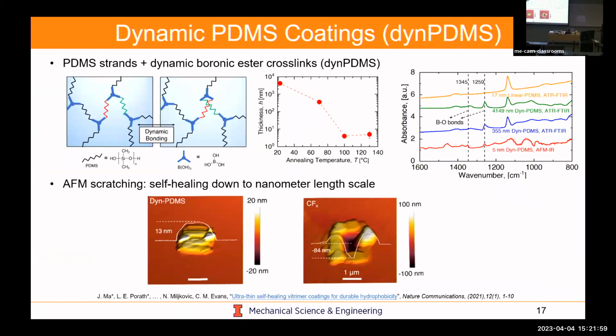We collaborate with a material scientist named Christopher Evans, not the actor, it's an actual material scientist at UIUC. We use PDMS strands with dynamic boronic ester crosslinks. We call this dynPDMS or dynamic PDMS. And so this is the way the cross-linking works and dynamic bond exchange. But really all we did was look at the processing parameters of how we can reduce the thickness and how that varies as a function of annealing temperature. We use things like FTIR or AFM-FTIR to actually look at the fact that these B-O bonds still remain, even as we go down to very thin formulations.